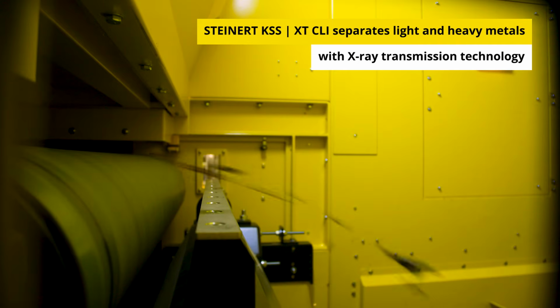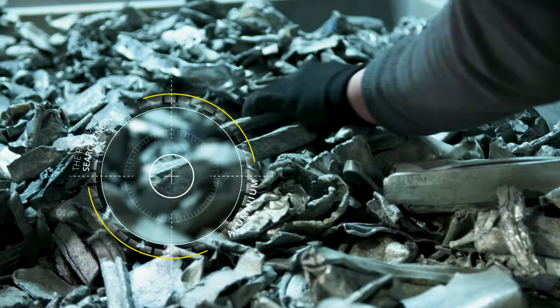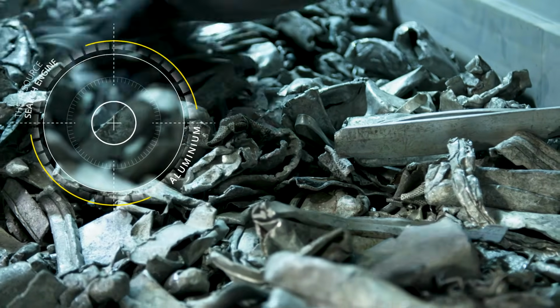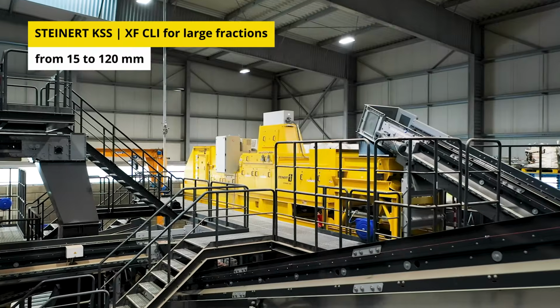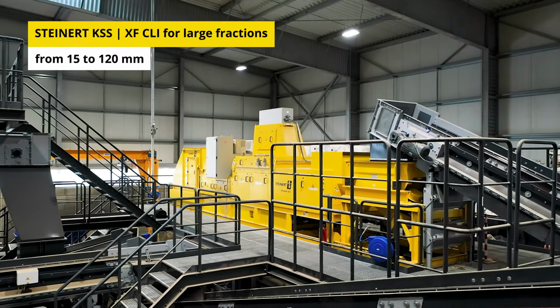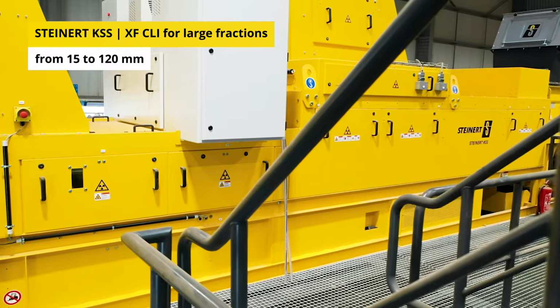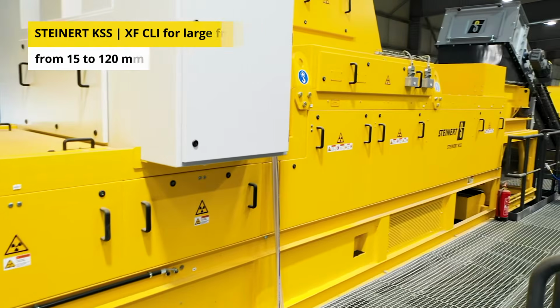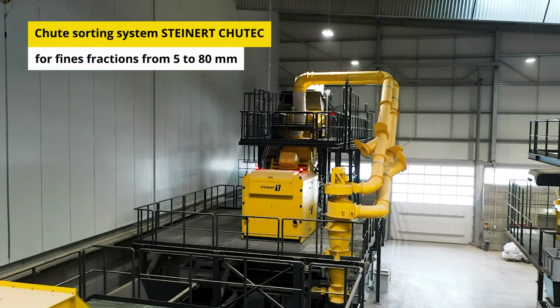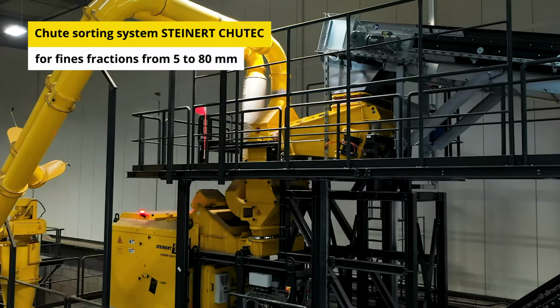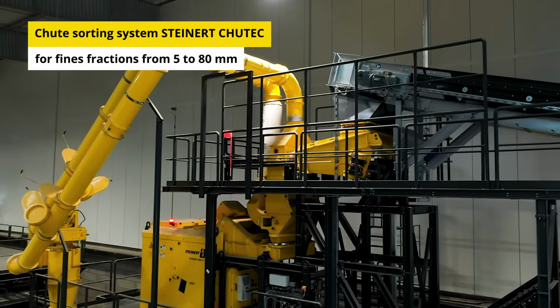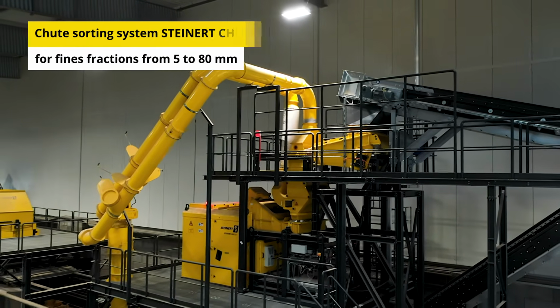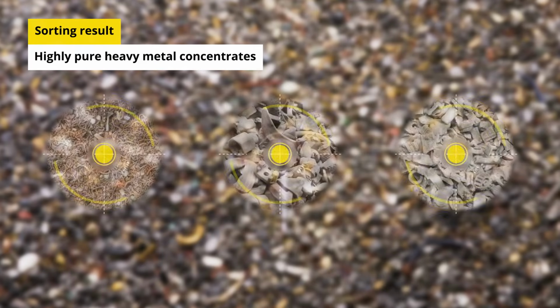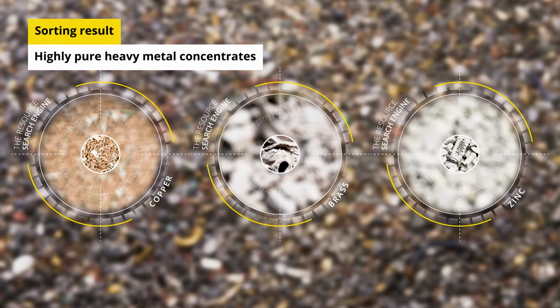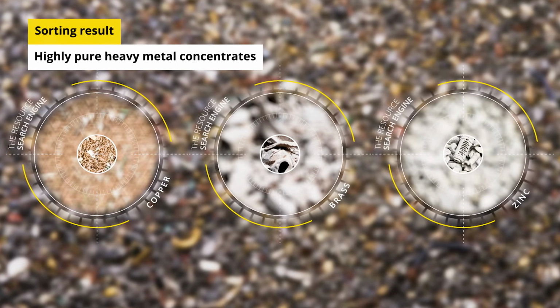In the first step, heavy metals like copper and zinc are removed from the aluminium mix by using precise compressed air blasts to move targeted pieces over a splitter plate at high speed. While coarse particles of a heavy non-ferrous concentrate can be processed with our STEINERT KSS XF, fines can also be treated using X-ray fluorescence technology with the STEINERT CHUTEC. XRF allows us to produce clean metal packages based on elemental composition, like clean copper, zinc or brass concentrates.